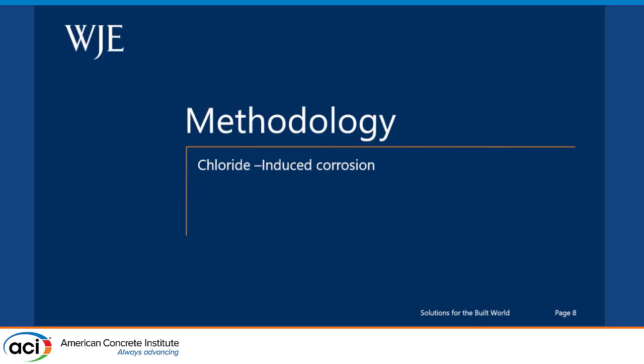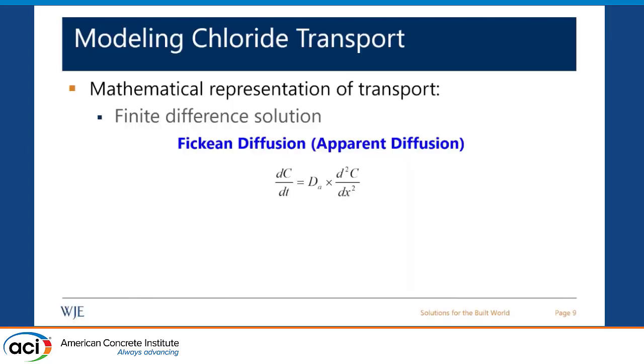Going into the methodology of our model, and based on the cases that we are given, here we're focusing on chloride-induced corrosion. So I'm not going to present on our capabilities on carbonation-induced corrosion, but rather focus on chloride-induced corrosion. We use a finite difference solution to Fick's second law of diffusion. This is similar to what Mark presented earlier on Life-365.